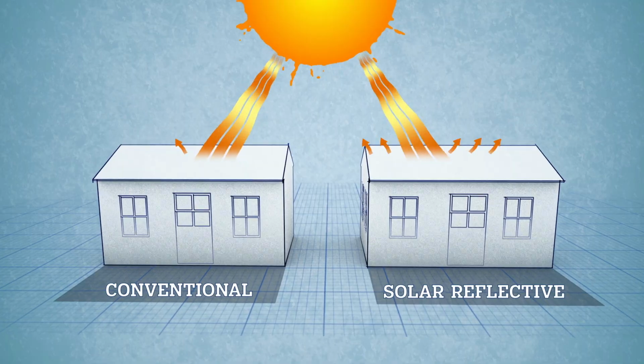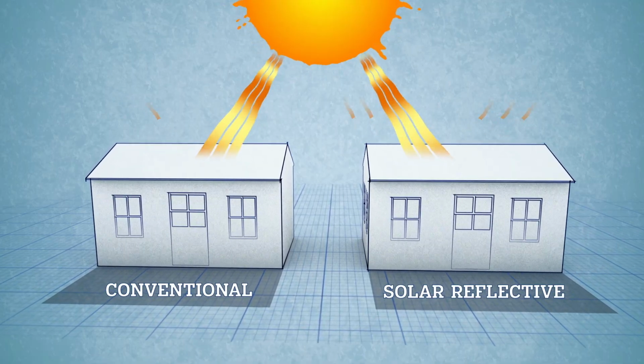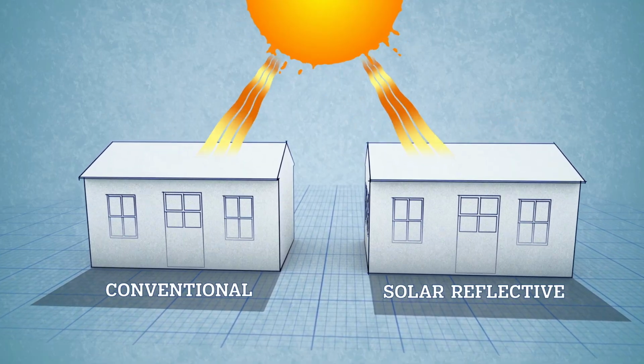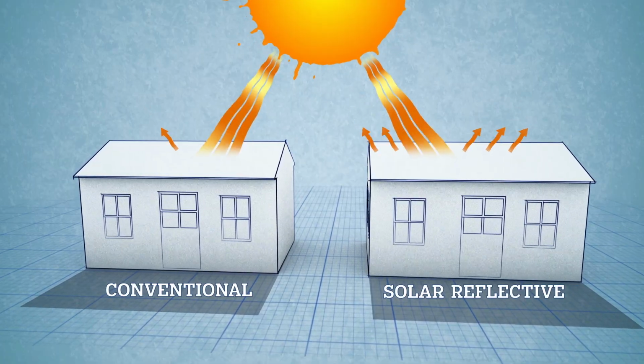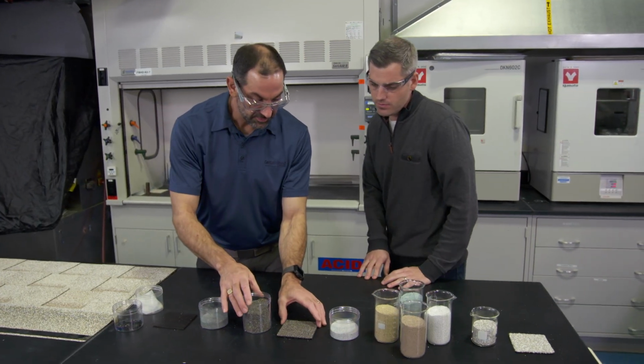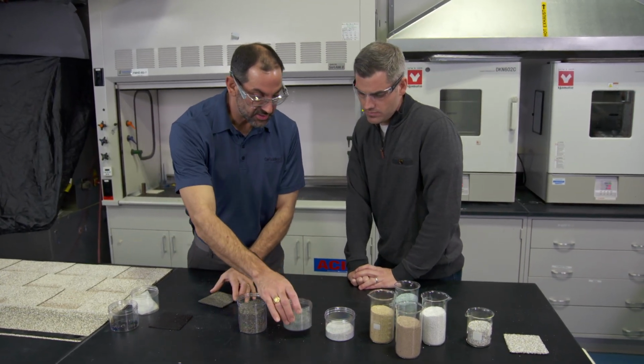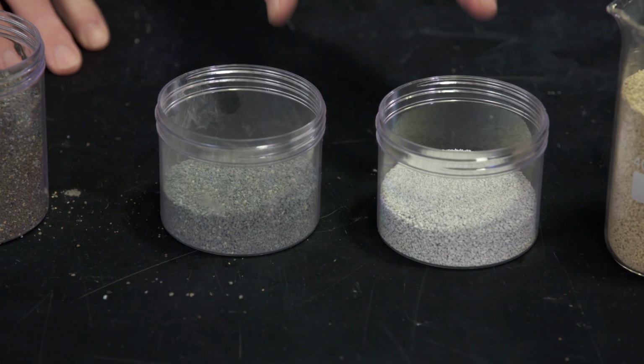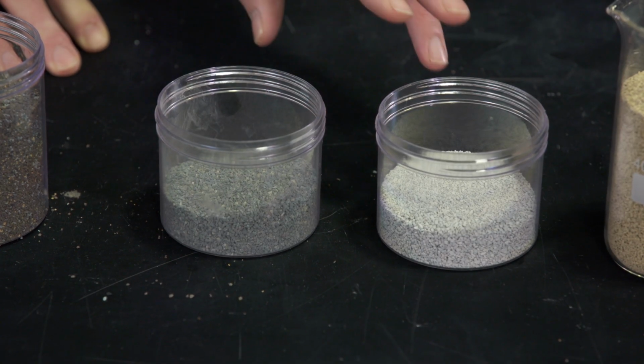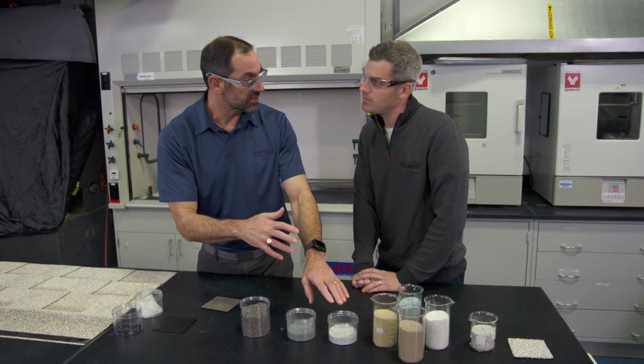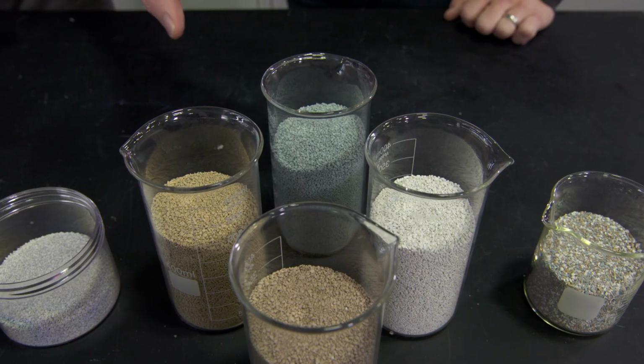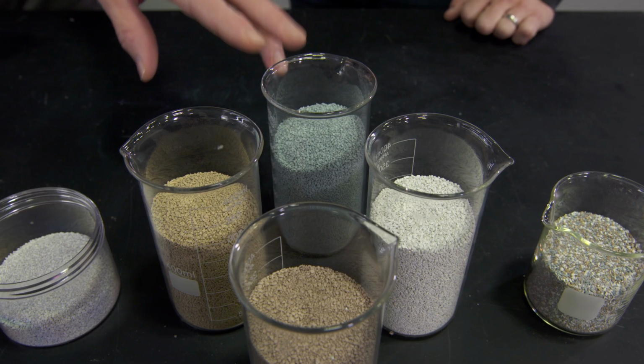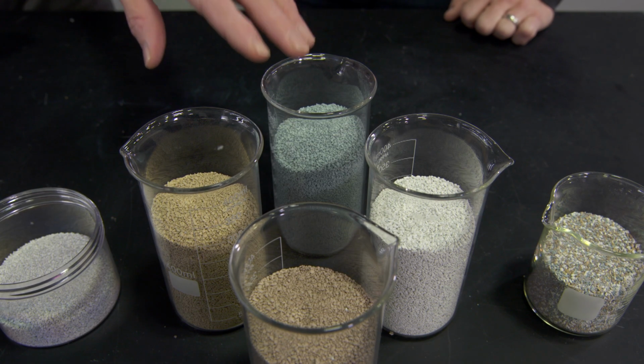This gives you the same overall look from the ground, but more than doubles the amount of infrared energy being reflected. In order to boost that solar reflectivity even higher though, Todd's team had to change the way they manufacture those granules. We can actually start with the base rock, put our first white coating onto that base rock, which adds that highly reflective layer onto the rock. On top of that coating, we can add a colored coating with our pigments. Any infrared light that passes through the color coating will then reflect off of that white coating to give it that boost in solar reflectivity.